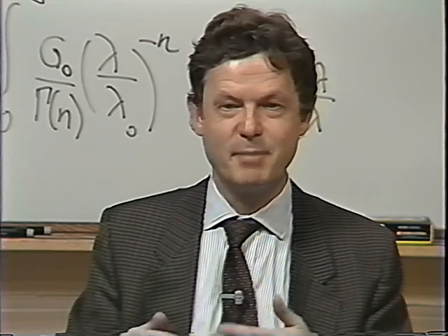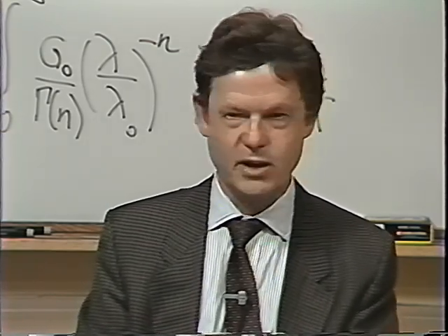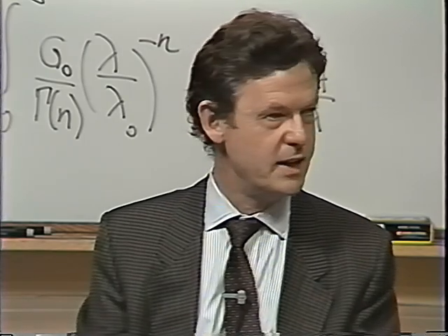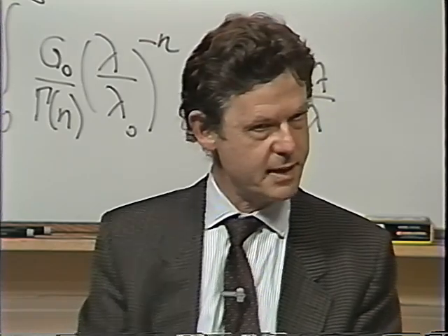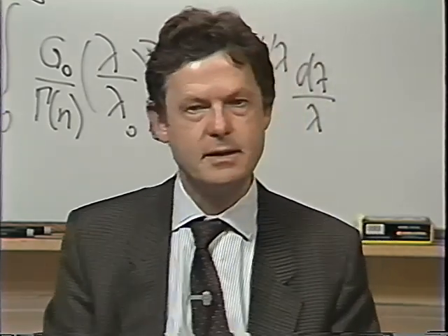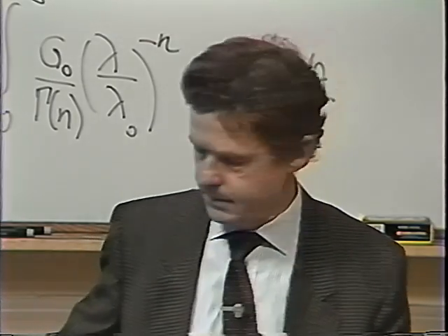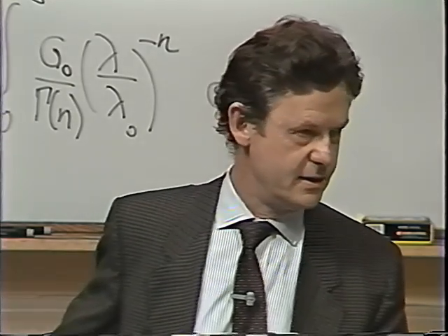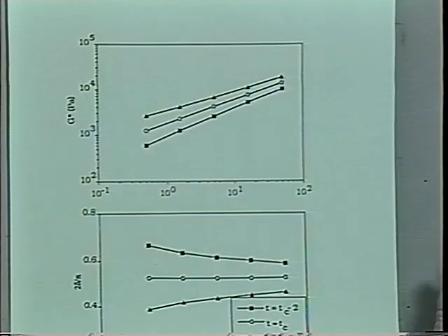Maybe the power law behavior is inherent in all our samples, and then we find tan delta constant in the whole spiel, the whole variation of that. Okay? But in an abstract sense, if you just get tan delta being constant, you don't know whether you're really in a power law state. We use that information anyway, because in our case, we know that tan delta constant gives us the gel point.